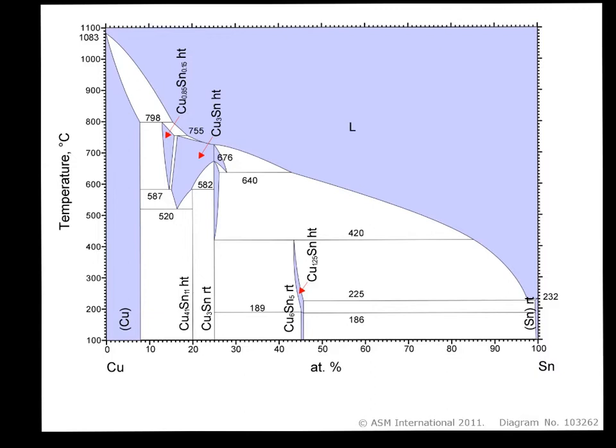And what happens is that you start with solid copper and solid tin at room temperature, and this is usually deposited so that you have a layer of copper, and then you have a layer of tin, perhaps on top of another layer of copper, among other things. These are pressed together and heated up, and so this starts to react. And so if this is done at a temperature below the melting temperature of tin, which is relatively low, right,